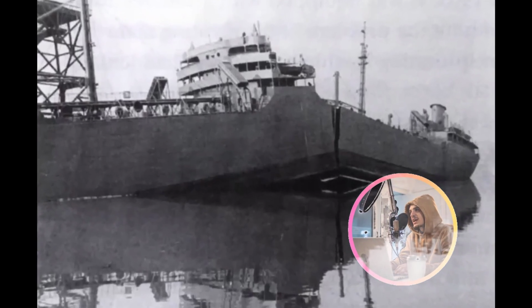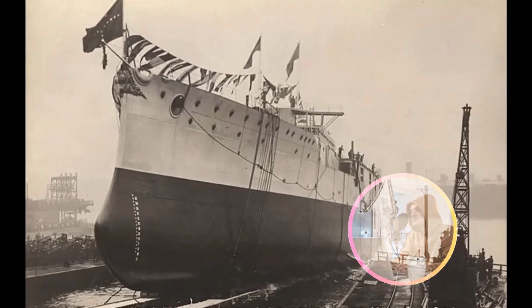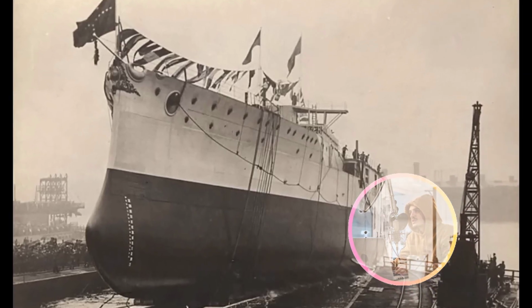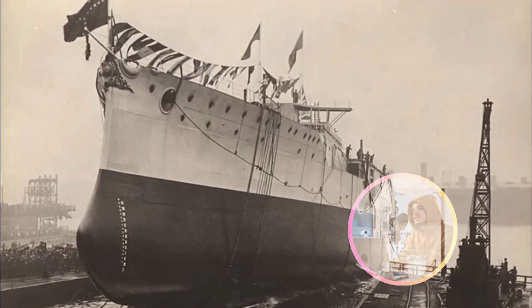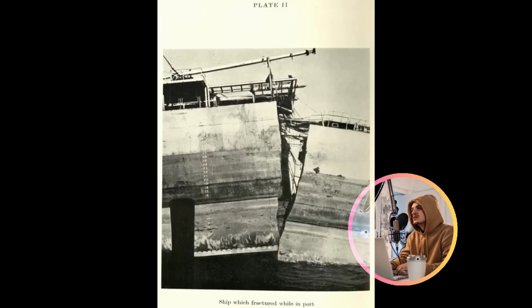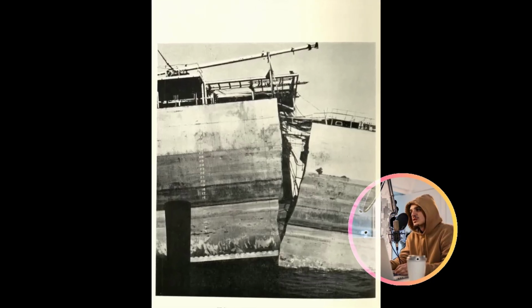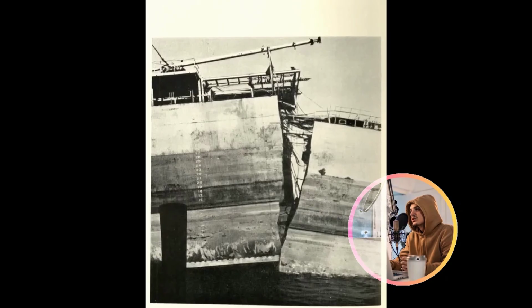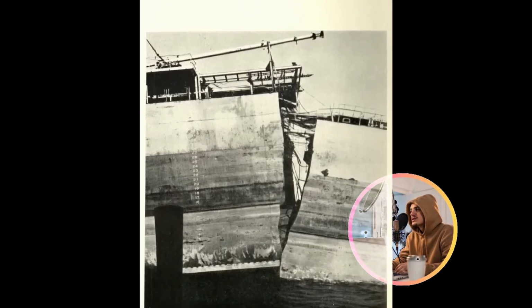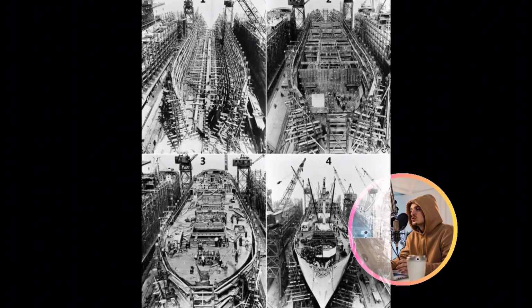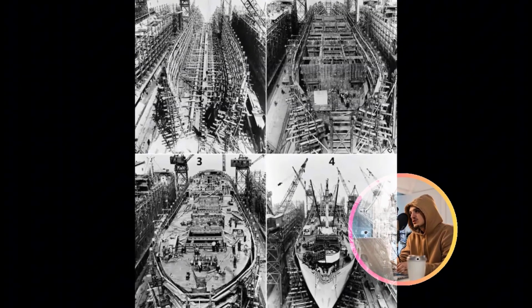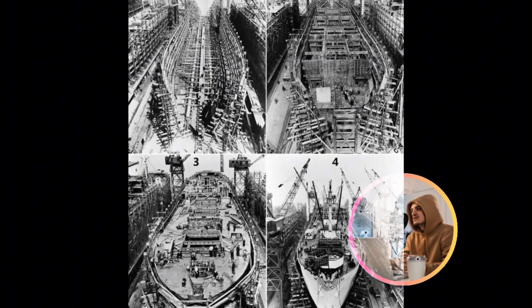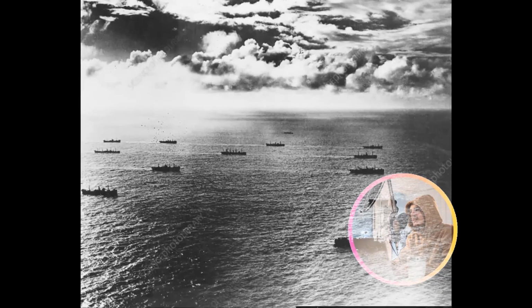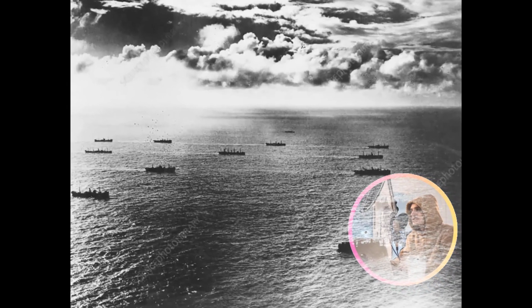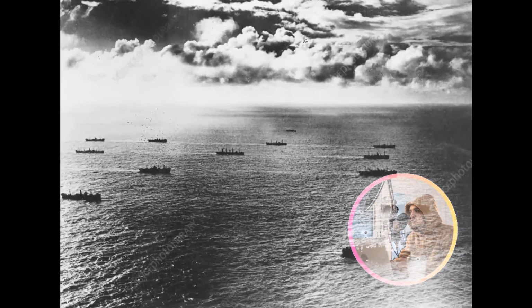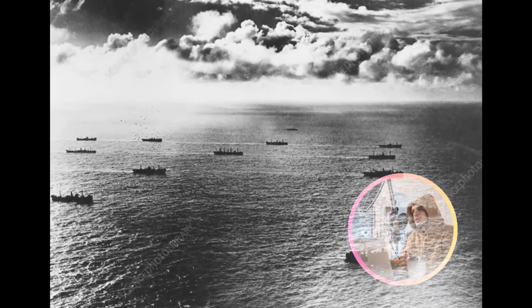Initially, the rejection rate for welds was notably high, with nearly 15% of welds failing inspection in the very first Victory ships. However, through intensive training and experience, the welders rapidly assimilated the new procedures. By mid-1944, the rejection rates had plummeted to below 3%, a powerful testament to the efficacy of the rigorous training programs and the exceptional clarity of the newly implemented welding procedures.